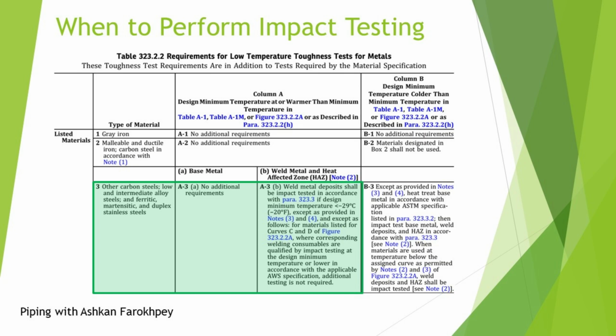welds can be ignored. Based on what is mentioned in column B, when the specified materials on the left are used at temperatures colder than their minimum temperature of table A1, the base material shall be heat treated according to related ASTM specification. In addition, the base material, weld deposit, and HAZ shall be impact tested. Plus, those relaxed materials at the note 2 and 3 of the curved figure we talked about previously shall also be impact tested on their weld deposit and HAZ sections.